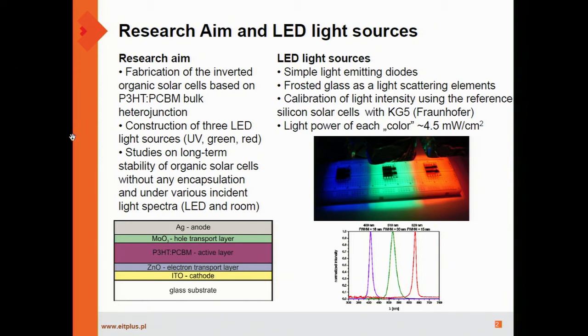We used a glass substrate with 100 nanometers of ITO. We deposited a zinc oxide layer by spin coating, and the active layer was also spin coated, but under a nitrogen atmosphere. The last two layers were thermally evaporated.